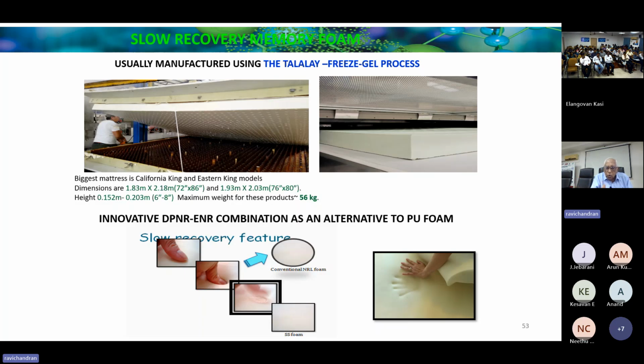Then we have slow recovery foam that we have introduced using a DPNR ENR combination. Normally latex foam, when you press it and leave, fully recovers instantly. But some of the PUs, when you press it, recover slowly. So we have now been able to simulate this with natural rubber foam using a combination, because ENR has high damping properties. So it damps the recovery process, and the DPNR also helps in that process. So this combination gives you a very sustainable, protein-free latex.